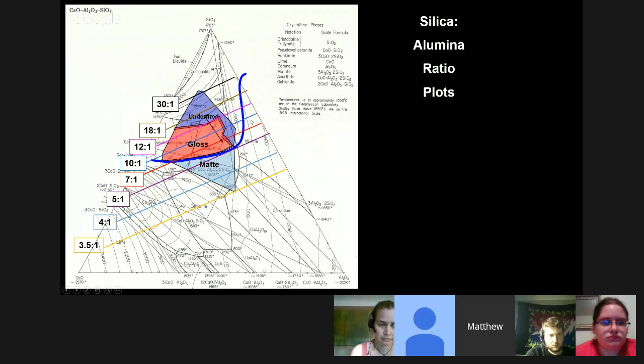It becomes more about the glass formation boundary, which separates glass from precipitating crystals. Now, in the firing, this is all glass. Everything in our composition is glass. But in the cooling, it precipitates crystals, and that can track with the phase diagram. Even though the phase diagram does not document glass, that doesn't mean these materials are not melting and then crystallizing on the cooling.